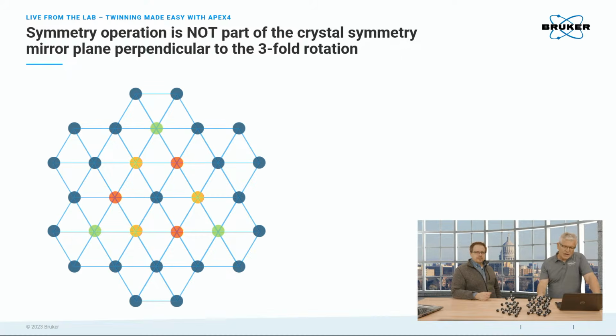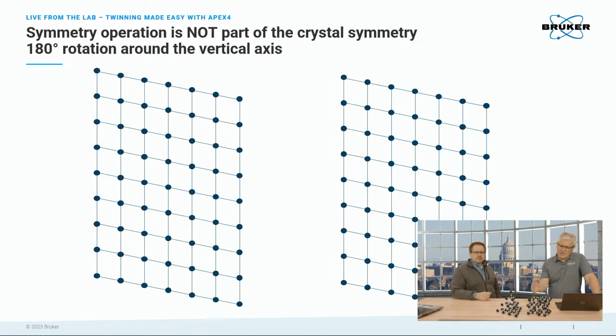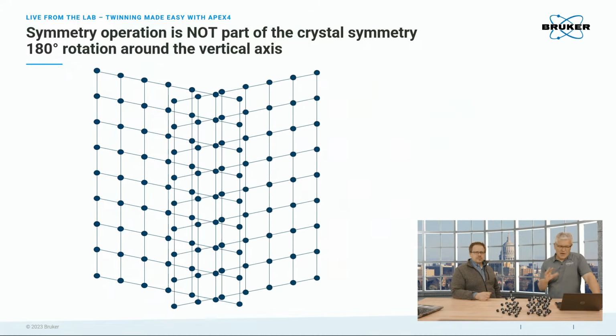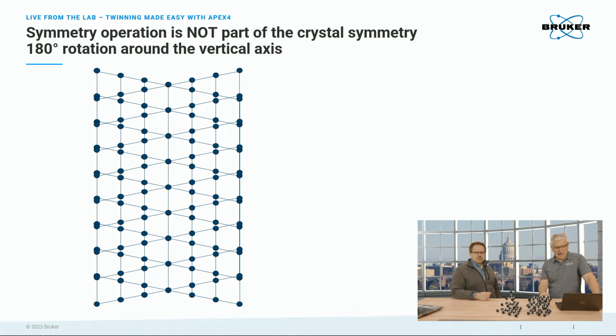Then if we go to lower symmetry, in this case something monoclinic, you see we have an angle that's not 90 degrees. I did a rotation by 180 degrees. When we overlap them, you see we have sort of a mess. Especially if you didn't have the lines there. Unfortunately, when you look at diffraction patterns, the software is not good enough to overlay lines right away. That's basically what you get from indexing. But you can see here, this is where the lattice planes are shared in the crystal, so they overlap. Then we have pairs, closer pairs, and then they get really close.